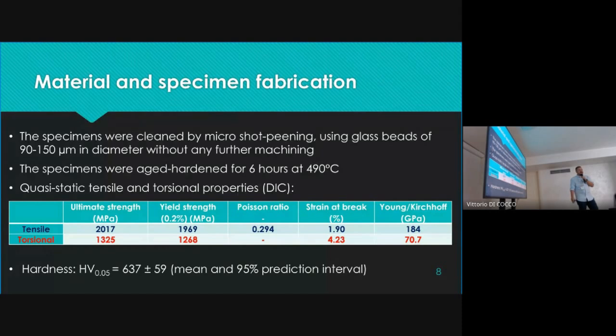Then they were age hardened for 6 hours at 490 degrees. We did a lot of tests to check the best temperature for this, and it turns out that the one the manufacturer says is the best was actually the best for the fatigue life. So we stayed with 490 degrees, and using DIC, besides standard methods too, we got the Poisson ratio and other parameters for the steel. So, a very durable material. As you can see, the ultimate strength is over 2 gigapascals. The yield strength is close to 2 gigapascals for tension, and 1,300 and 1,200 for torsional stresses. The hardness is around 650.